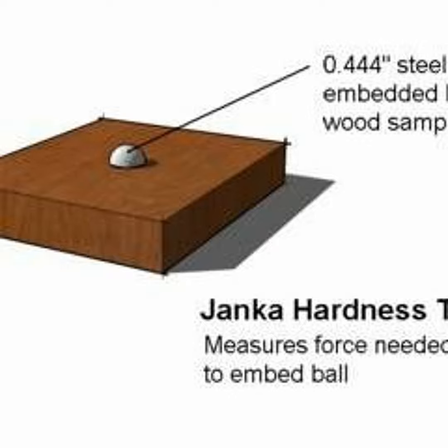So what does that really mean? Anybody who's worked with genuine mahogany and hard maple knows that genuine mahogany is a lot easier to work, yet the densities are close to the same. And this is because genuine mahogany has some larger pores. There's more dead air in the wood. So the material that's left, the lignin that forms the stuff around the pores, is actually quite hard. But you'll find that the Janka hardness is quite a bit lower because the dead air in there allows the whole thing to feel a lot easier to chop against.